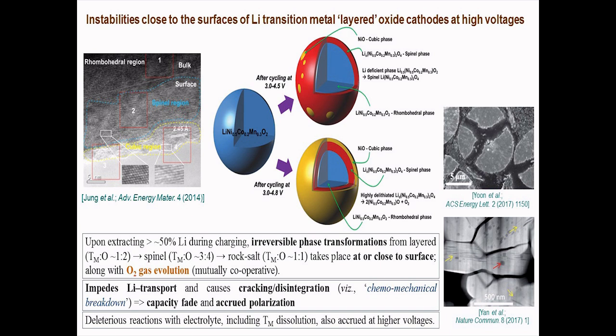Again, a very similar material, lithium transition metal oxide, something which is used nowadays in most lithium-ion batteries. That also undergoes phase transformation from the layered structure to the spinel to rock salt structure, starting from the surface of the material. And if these non-layered structures form, they create a lot of hindrance towards the insertion, deinsertion of the lithium ion, which is bad for the stability of the electrode over multiple lithiation, delithiation cycles.